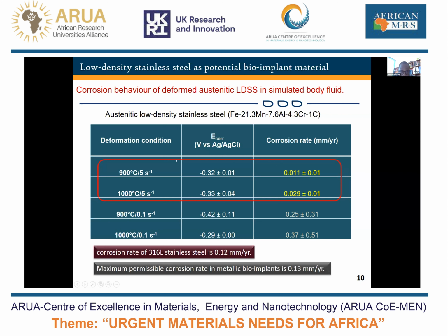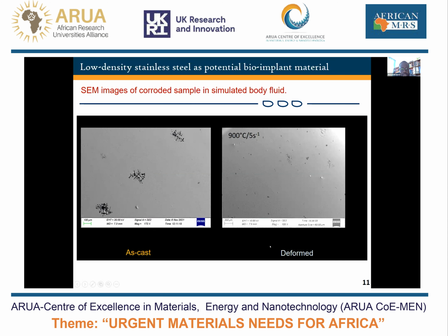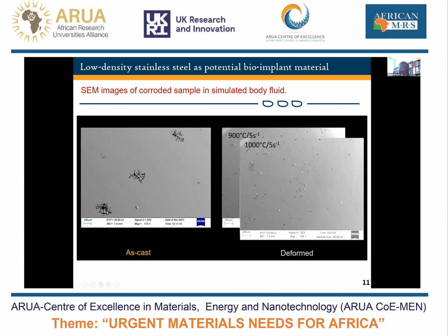But for these conditions, we still see that the corrosion rate was 10 times lower than the 316L stainless steel, and of course was lower than the maximum permissible corrosion rate for bio-implant alloys. So we looked at the microstructure of those particular samples, and we could see that we were able to reduce the effect of pitting, and this is another microstructure confirming that.